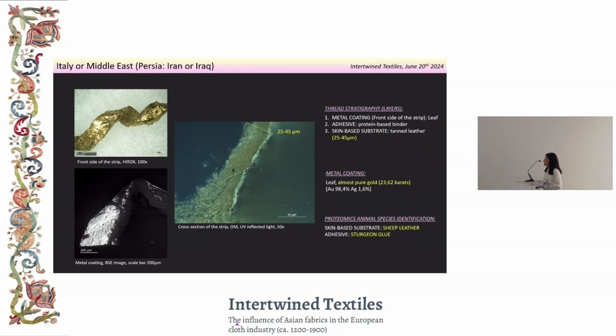Microanalysis, in this case, for all the samples like this, shows that the coating was almost pure gold, and the stratigraphy of the strip is very basic. So we have a metal coating, the number 1 you can see, then the adhesive layer, and then the strip. In this case, the strips were much thinner compared to the Asian flat strips. But again, proteomics tells us that they were made with sheep leather. And again, the adhesive we used was sturgeon glue.